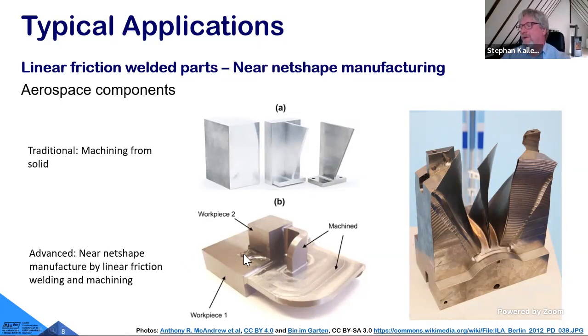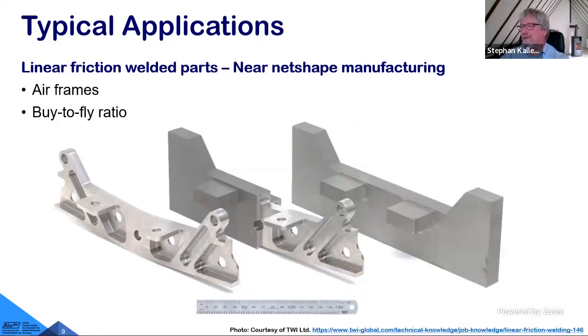And by that, we first of all get rid of the flash. We get rid of any kissing bonds or unwelded regions at the edges of the workpiece. And we have finally a part that meets our specification. Here you see an aerospace part on the right-hand side that has been made from 3 components. Little blocks onto the substrate, and then finally we machine this little bracket or tab out of the component, and